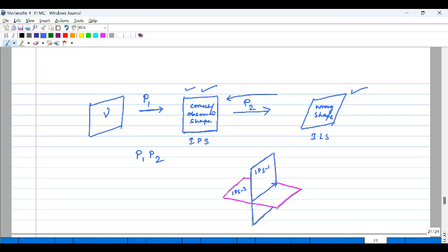Since it's an invariant plane strain, but we need an invariant line strain for the austenite to transform to martensite, we can add another invariant plane strain, which is again a shear that would give rise to an invariant line strain, which is also the same as this. A combination of Bain strain and a rigid body rotation had also given us the same thing, an invariant line strain.